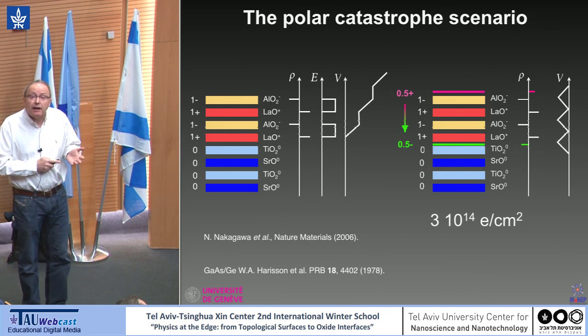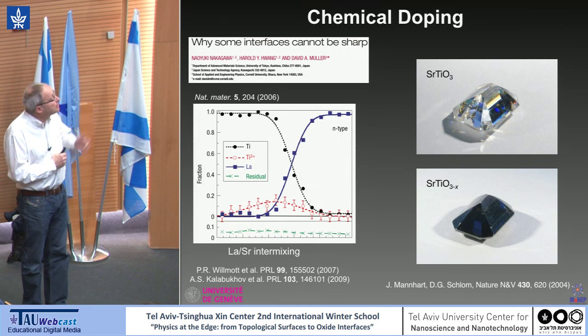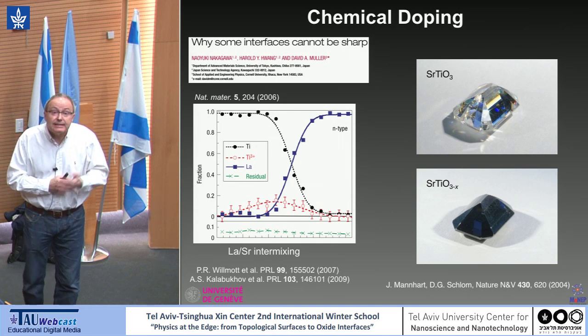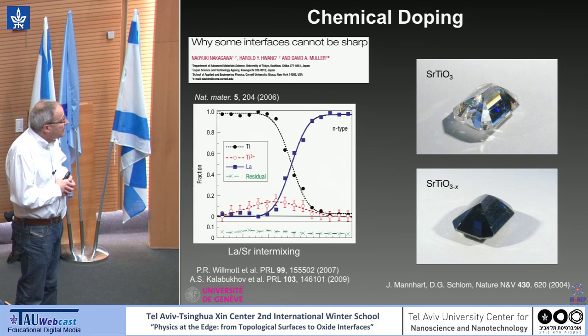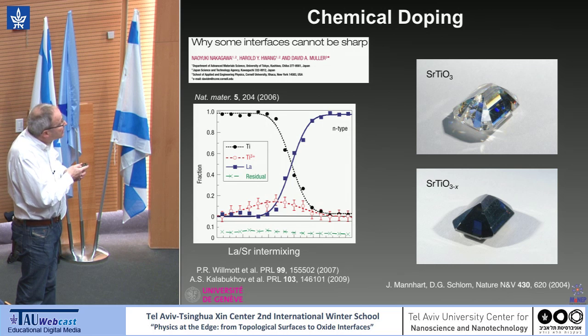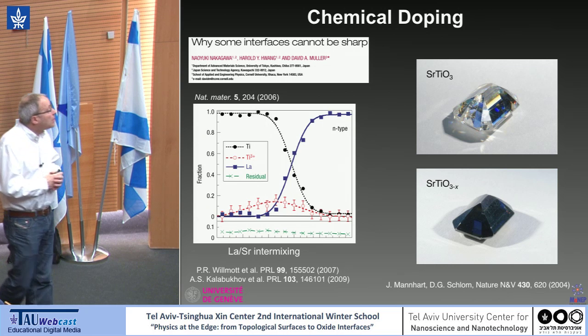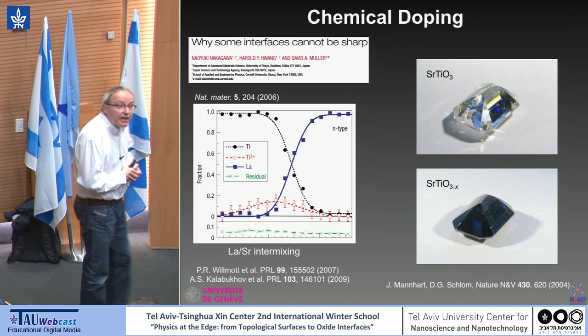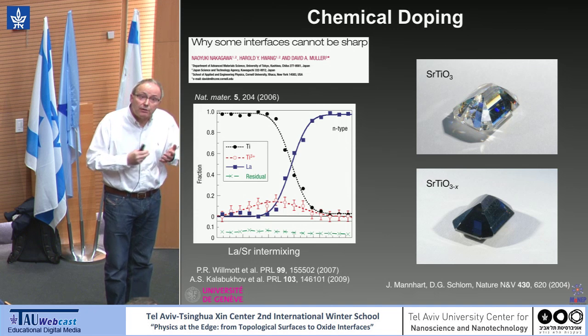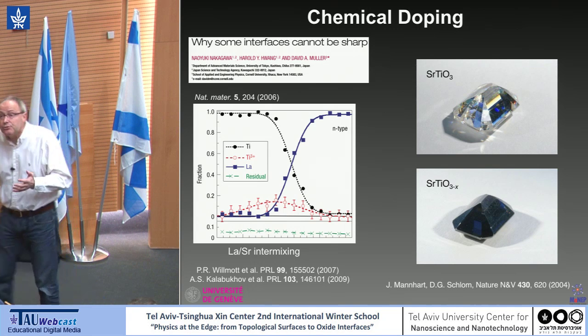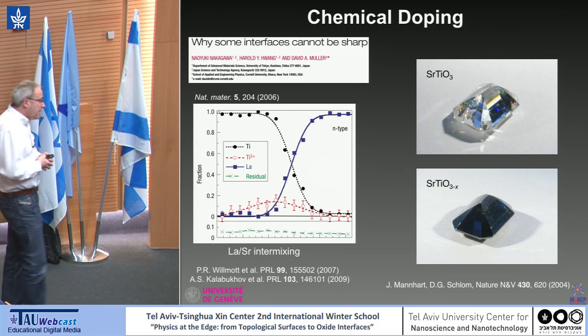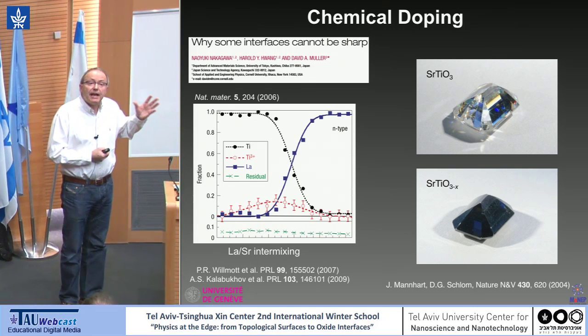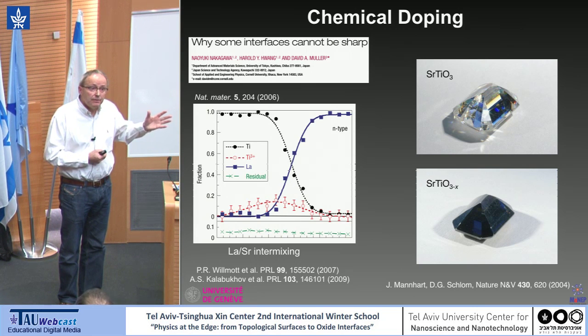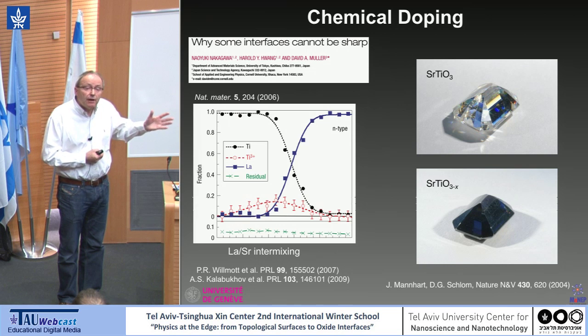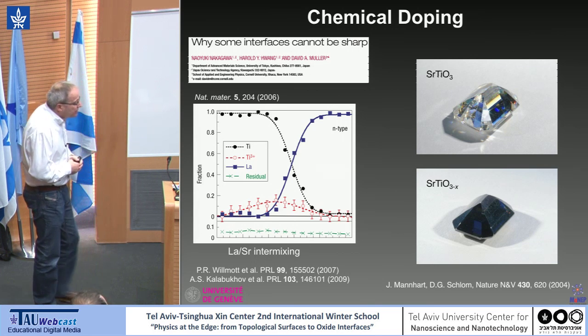Now, other scenarios have been discussed a lot, in fact. The possibility that lanthanum-strontium intermixing at the interface is playing a role, and in fact we have some intermixing. This is again a paper of Harold Hwang and co-workers. Oxygen vacancies have been discussed a lot, because one knows that in strontium titanate it's quite easy to generate oxygen vacancies. Maybe one thing to say is that these scenarios can bring conduction, but they do not solve the polar catastrophe problem. Because to solve this problem without off-stoichiometry, we really have to transfer charges from one side of this capacitor, in quotation marks, to the other side.